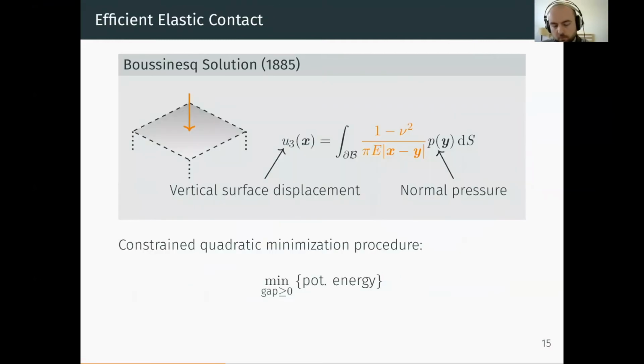So I've talked about methods that work really well for elastic contact with multiscale roughness, and those are boundary integral methods. And they revolve around the principle that you can express equilibrium surface displacements as a function of contact pressures using this convolution integral here. And the kernel you use for this convolution integral is the displacement that is due to a point force acting on a half space that is elastic. So if you can write your equilibrium using this equation, you can also write your potential energy, and elastic contact basically becomes a minimum principle of minimum potential energy under the constraint that the separation of the two surfaces should be greater than or equal to 0.